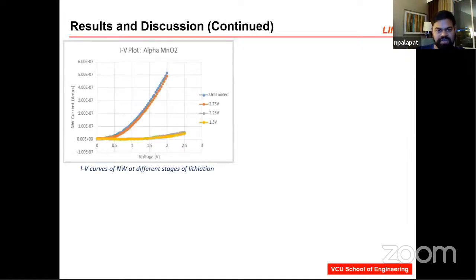So here is a graph at all these different stages of lithiation that I talked about. And you can see that the more lithiation you do, the output from your nanowire material system degrades quite a bit, which is what you see in your battery, right? When you discharge your battery quite a lot, at 5%, there is nothing left in your battery to give out any power. So these are some electrical measurements that are performed. What information can we gain out of this? As we increase the lithiation, we see an increase in resistance, thereby a drop in your conductance.